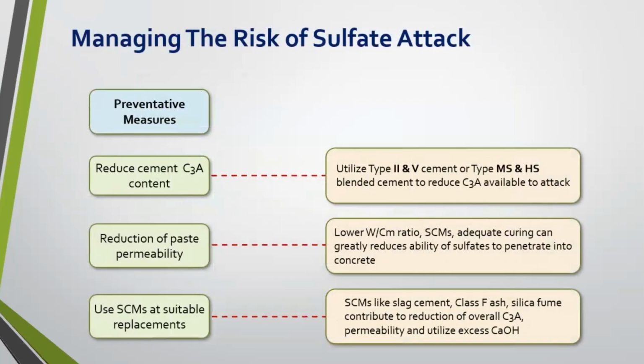So just a quick summary, talking about managing the risk of sulfate attack. Some of those preventative measures are this. We are reducing the cement C3A content. We can do this utilizing a C150 type 2 or type 5, or a C595 cement with an MS or an HS designation. We're reducing that C3A available. Reduction of paste permeability. This is super, super important. Anytime you lower the water cement ratio, obviously you're reducing permeability in your concrete, and you're making it harder for those deleterious materials to reach the paste.